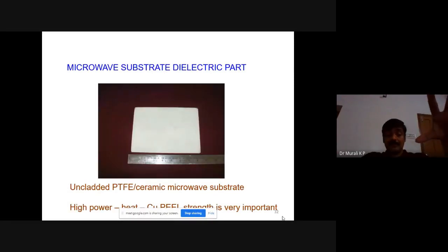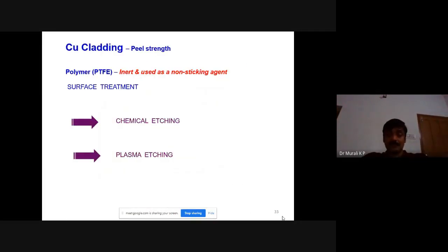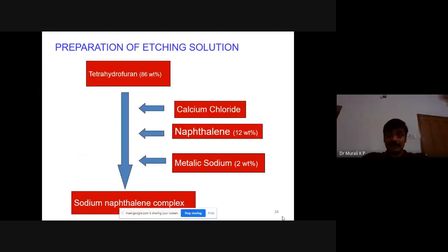Another very important thing is how to clad, because most of the plastic, I mean polymer materials, are highly inert, so it is very difficult to stick a metal onto them. There are two techniques which are used. First, we can surface modify the polymer. In the case of PTFE, we attempted chemical etching as well as plasma etching. The difficulty we faced with chemical etching is that the chemical etchant we prepared has very little shelf life, so it is very difficult to keep the etching solution active.